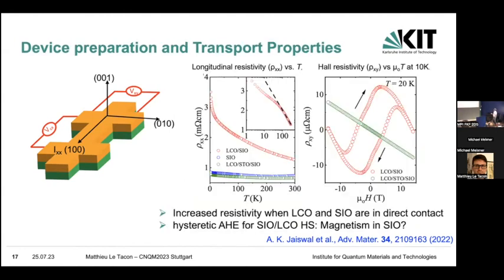So we looked at the resistivity, and what you can see is that when strontium iridate is alone, you get this semi-metallic behavior. And when you put LCO and separate it from the SIO with an STO layer, you also have the semi-metallic behavior. So the transport is really dominated here by the iridate layer. But when the lanthanum cobaltate and the strontium iridate are in direct contact, you see an increase of the resistivity. It's still conducting, but it's less conducting.